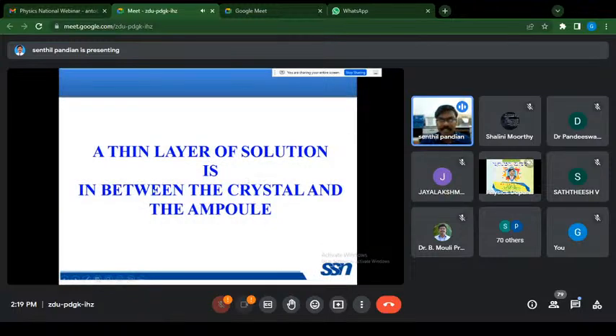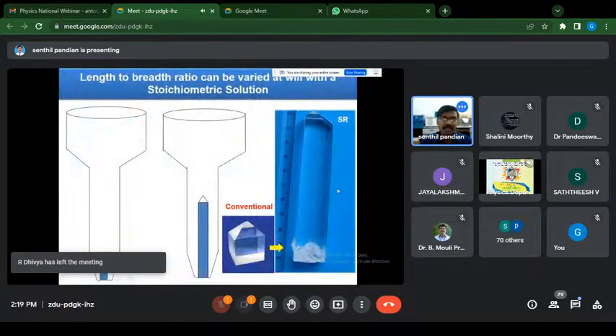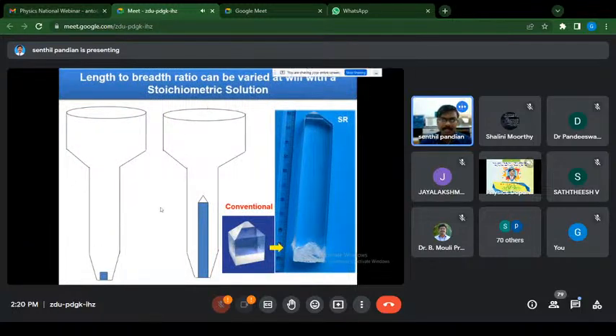A thin layer of solution is in between the crystal and the glass ampoule, so there will be no mechanical stress in the grown crystal. The length to breadth ratio can be varied with a stoichiometric solution. This is the normal KDP single crystal, potassium dihydrogen phosphate single crystal, grown by this conventional method.